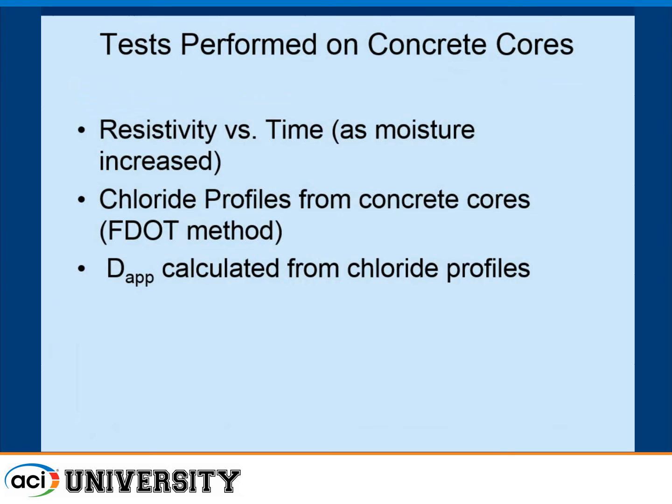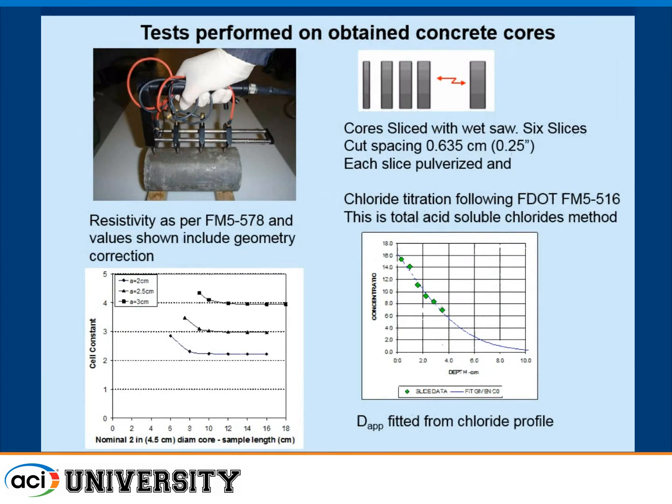In addition, on those cores, we performed resistivity versus time, and we increased the moisture until the values were stable. And then, as I mentioned earlier, we obtained chloride profiles from those cores, and from those profiles we estimated the apparent diffusivity. The resistivity was measured by the Wenner probe approach following FDOT FM5-578.